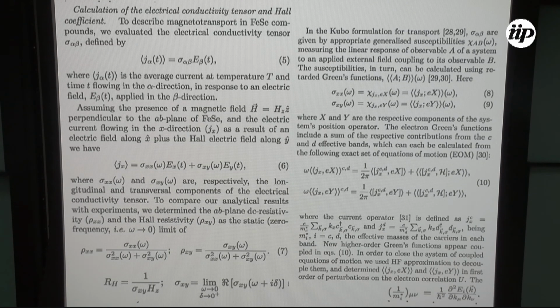Let me just mention, because of the time I have, how we do the calculation of the transport. We are basically using linear response correlation functions, and we are using the Kubo formulation to obtain the different components of the conductivity tensor and the resistivity. And then, having this transversal conductivity, we can also obtain the Hall coefficient.